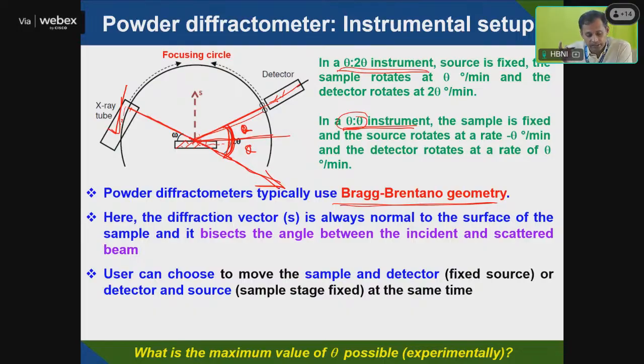But if you go to single crystal XRD, there the sample will move, the source will move, the detector will move, and the stage will move. There will be a 4 angle or 5 angle rotation in the case of single crystal XRD. But in powder XRD, only the source and detector are moving. So there can be 3D mapping in the case of single crystal, but you can't get 3D mapping from powder diffraction. Okay. 3D mapping is only possible in the case of single crystal XRD. Okay.